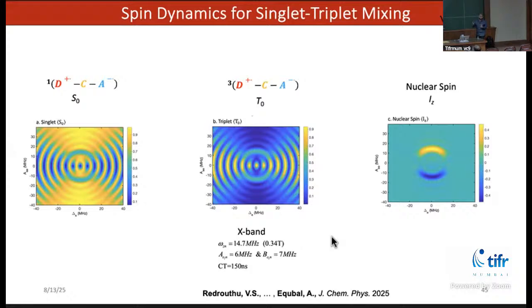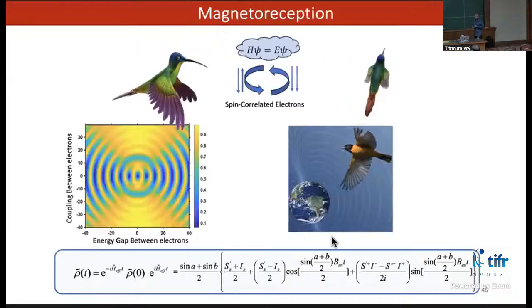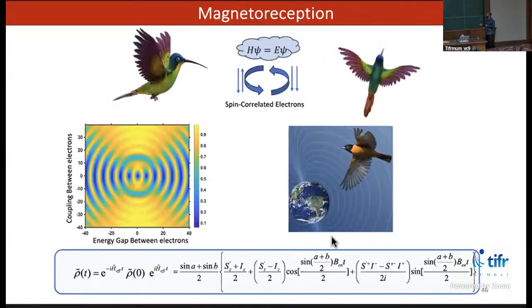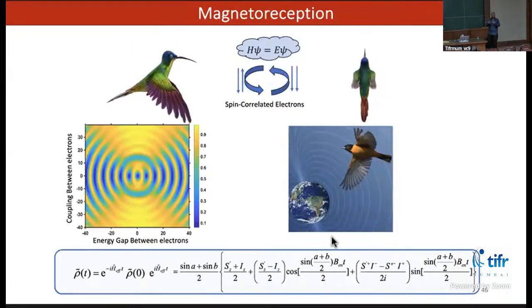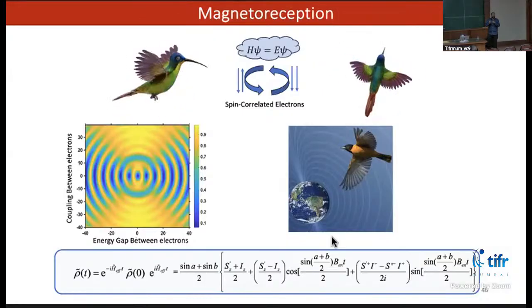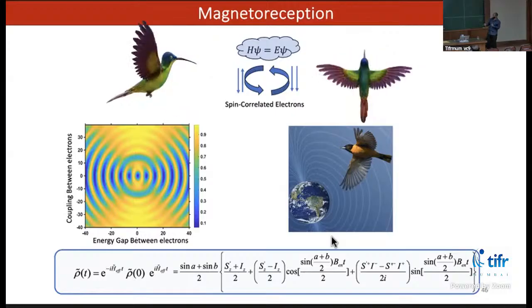When would that 3-spin mixing lead to nuclear spin polarization? What was most exciting at the time we were working on this is that the same spin-correlated radical pair singlet-triplet conversion using nuclear spin, the same mechanism, has been proposed to be applicable for magnetoreception.